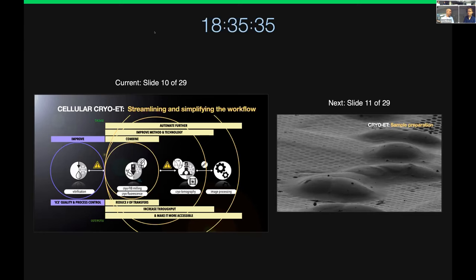or more. Sven: So the only thing that can tell you this is the Z-dependent B factor plot, where you take ribosomes, for example, in a certain volume of your tomogram, and then average those and look at how many ribosomes you need to reach a certain resolution. This experiment has not been done yet. I know that there's a supplementary figure in a recent bioRxiv preprint by the Rosalind Franklin Institute, where they have first indications that yes, there is damage. They took the ribosomes that are 30 nanometers away from the sample surface and still saw an effect in terms of B factor. However, very explicitly, this experiment hasn't been done to the best of my knowledge. But I have to add that we are working on such a plot.